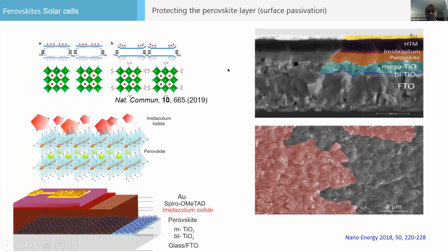So another molecule we did, in collaboration with Nazeeruddin also, is using an imidazolium iodide, because iodine ion migration is very common in perovskite solar cells. To fulfill this, we have used imidazolium iodide as a reservoir, and we passivate the surface.